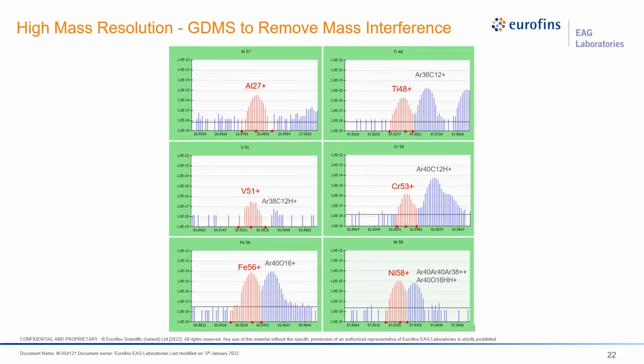One of the important requirements for trace analysis with mass spec is to resolve the mass interference. In the plasma conditions, not only will the analyzed isotope show up, but many polyatomic interferences, whether from the matrix or from the discharge gas, for example argon, can form.